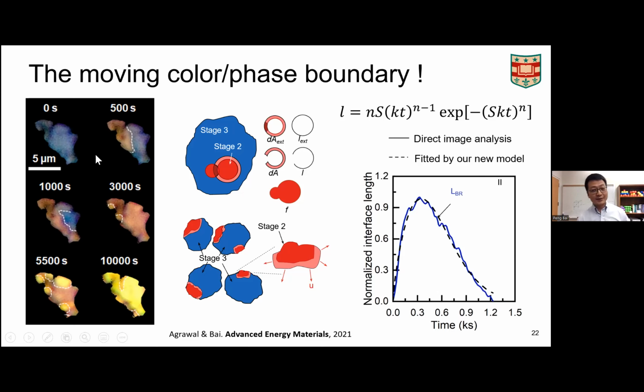And this is the time when more fundamental science comes in. When you see this phenomenon, can you translate this into a different language? The language of mathematics. And the language of mathematics is just equations. So we were able to model the system by using this equation, okay? And that equation can very accurately fit the curve. The blue one is the experimentally determined phase boundary, or color boundary, length. The total length is evolving, as you can see here.